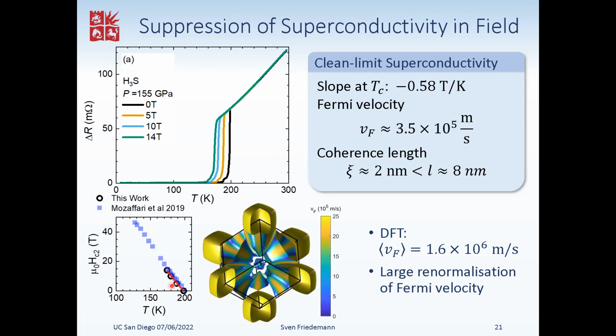And indeed, if we take the slope and just use the simplest single band BCS superconductivity, we can extract the Fermi velocity of the order of 3.5 times 10 to the 5 meters per second, and a coherence length of about 2 nanometers, which indeed is smaller than the mean free path that I extracted on the previous slide. So that's confirming that we've got clean limit superconductivity in these samples. At the same time, if we compare this Fermi velocity with DFT calculations, we can see that it is smaller. And indeed, it's close to what you expect due to the renormalization from the electron-phonon coupling, so you get a factor of roughly 1 plus lambda difference here.